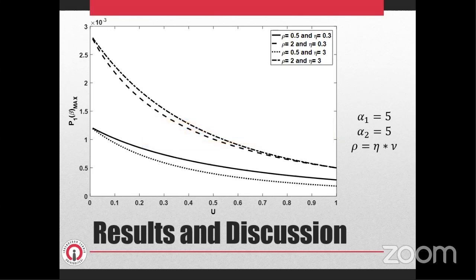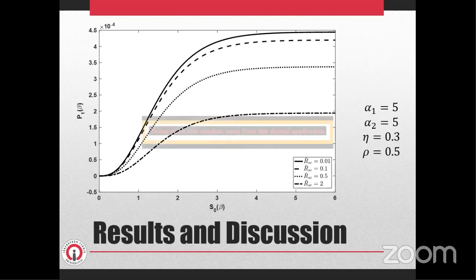These results suggest that selecting rho smaller, regardless of the value of eta, will have a stabilizing effect on the proposed stability mechanism. And lastly, this figure demonstrates the variation in contact pressure with the mean shell thickness for selected values of contact resistance at the shell coating interface. It can be seen that the increase in thermal contact resistance at this interface causes a reduction in the amplitude of the perturbation in contact pressure.